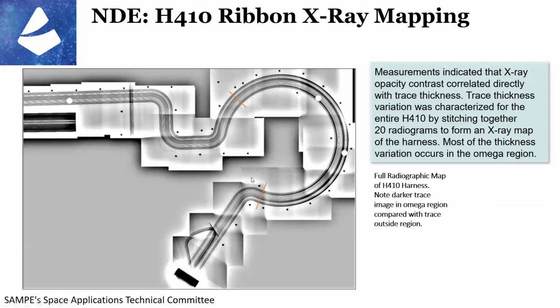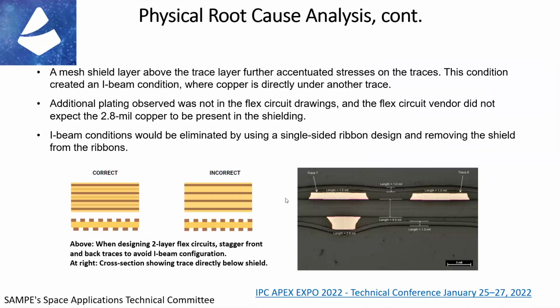One of the recommendations we were able to make is, you can see just by X-ray mapping, once you know what the problem is, it's pretty easy to see where it occurred, because these traces are much darker here and attenuating more X-ray versus the rest of the wiring harness, which was all nominal thickness. We found out later on that they had folded this harness over, and just this part had been plated a little bit more than the rest, which eventually created this I-beam flex problem, which is kind of interesting.